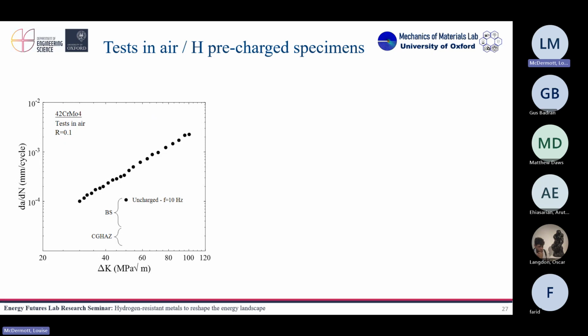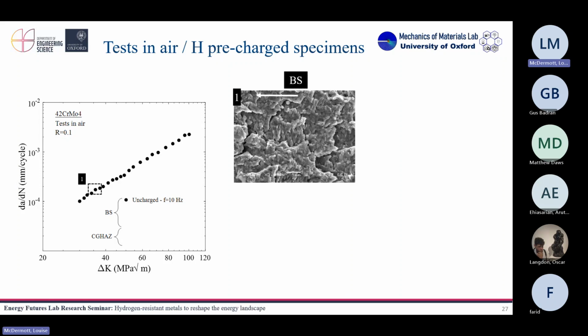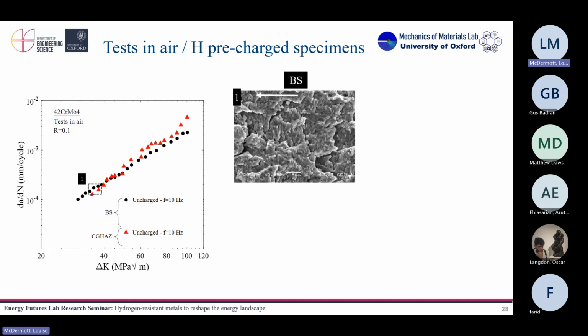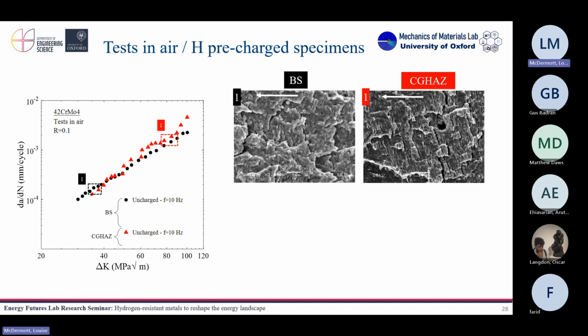So this is the behavior of one of my materials, because I compare two materials, one in the base metal and the other in the weld. This is the behavior of my base metal with no hydrogen. And if we go to the SEM and check the fracture surface, we see that all these striation marks are indicative of ductile behavior. So okay, no problem here. We tested then the weld. Remember, this is far from the weld and this is the weld. We had a similar behavior to the steel far from the weld, and we also see these striation marks. So that's the behavior.